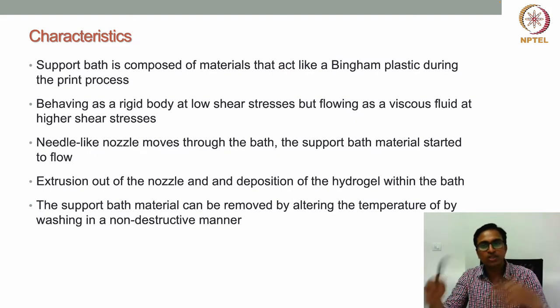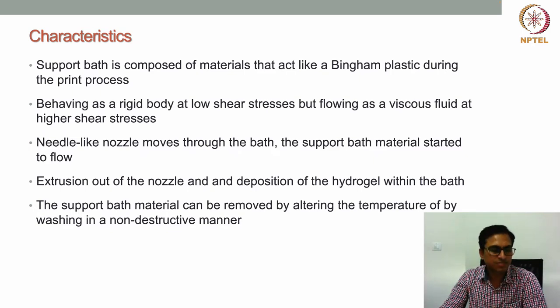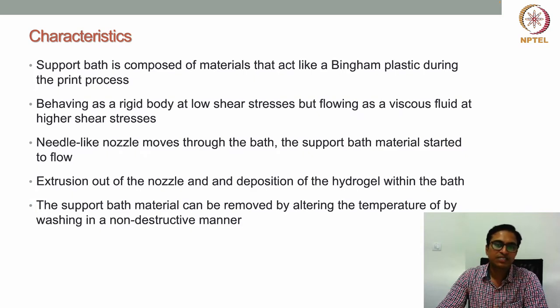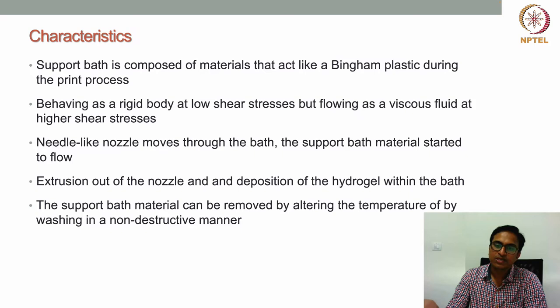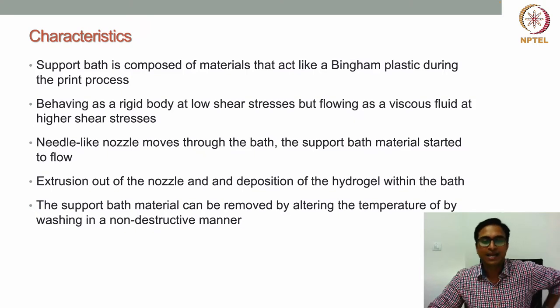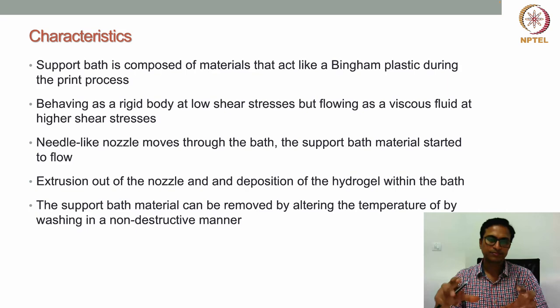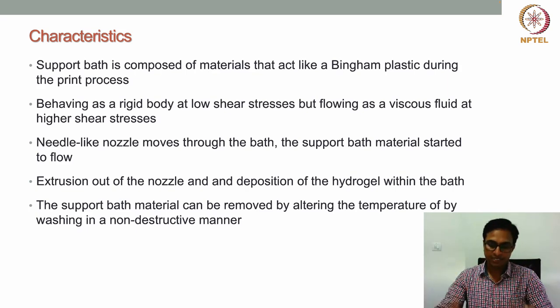After the entire printing process is done, how do we remove the support bath material? Mostly we use support materials that can be removed in various ways. One way is to use a thermoreversible material — one that behaves like a gel at a certain temperature and like a liquid above a critical temperature. If the support bath material is water-soluble or soluble in buffer or media, we can simply wash it away in a non-destructive manner.